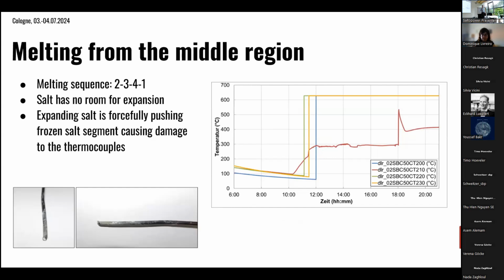And the next experiment was then starting with the second segment. So you basically have a frozen first segment, then you melt the second segment, and the third and the fourth segment was also still frozen. And now the salt didn't have any room for the expansion process. And as you can see, it forcefully pushed the salt aside. And what was happening here is we destroyed the thermocouples. So the force was so high that it was just cutting away the thermocouples, which were sticking inside the frozen segments. There's a picture of the thermocouple after it was just cut off.